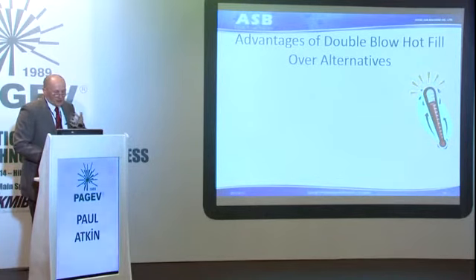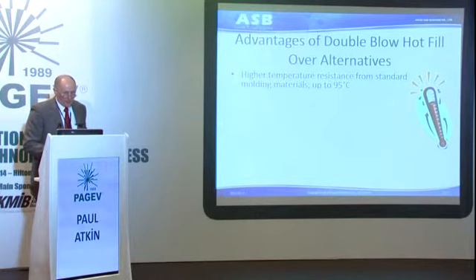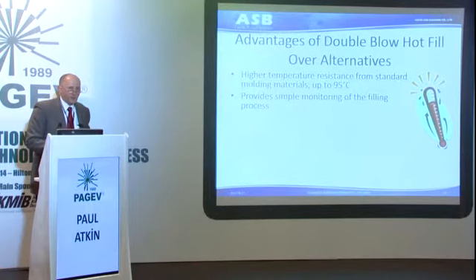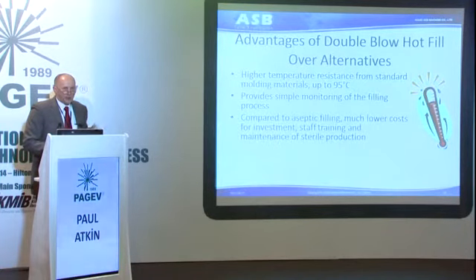So looking at all the advantages of double blow over various alternatives, the higher temperature resistance that we get allows us to go up to 95 degrees C with standard materials. And when you're doing hot filling as opposed to aseptic filling, the process of filling is very simple. All you have to do is monitor the temperature, and you know that your product is safe. With aseptic, there's a whole range of bacteria cultures to be taken and studied, and you have to hold your stock until you know that it's clear. Hot filling is much more simple. And what that means is that your investment costs, your training, your operation, all these costs are dramatically reduced.